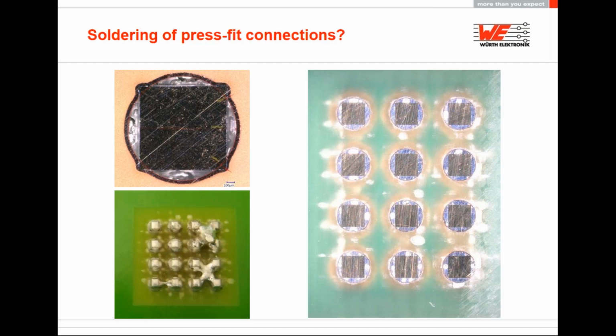This can affect soldering of parts placed close to the REDCUBE press fit elements on the PCB. A lot of the heat will actually go to the rest of the PCB and not to the connector, because we have a huge piece of brass which is absorbing the whole heat source and practically transferring it to the rest of the PCB. So it is not a good idea to solder press fit connections, because there are worst cases that can happen due to it.